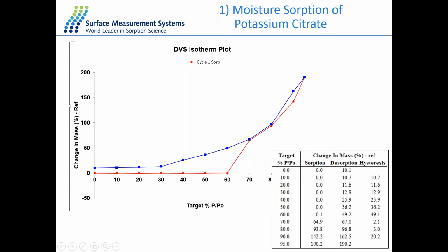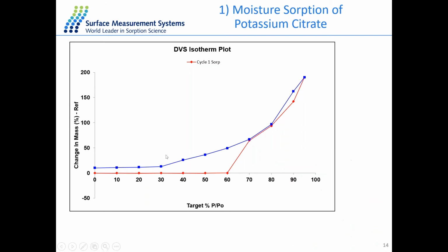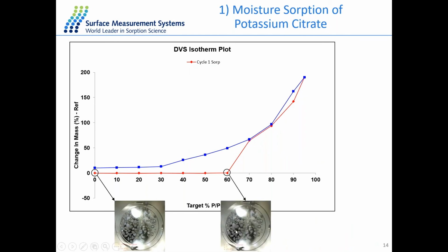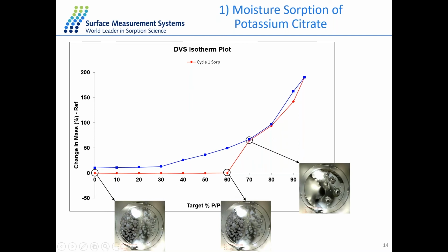So this is just the isotherm, and we also take the photo image at each percentage RH step. We can compare from the photo images that from 0 to 60% RH, the sample basically keeps the same original nature up to 60% RH. And then when the humidity keeps increasing above 60, it starts dissolving. And then the sample is fully dissolved at 95% RH.